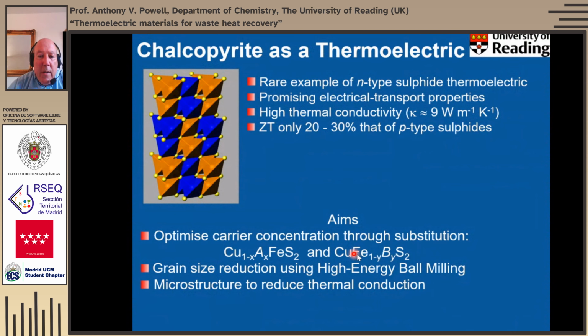So what we've been doing in a very recent project, and this is going on at the moment, in fact, some of this work was presented at the conference this morning, for example. We're trying to optimize the carrier concentrations through substitution either at the copper site or at the iron site in chalcopyrite, and combining that with grain size reduction using high energy ball milling, and also trying to use the microstructure to control the thermal conductivity.